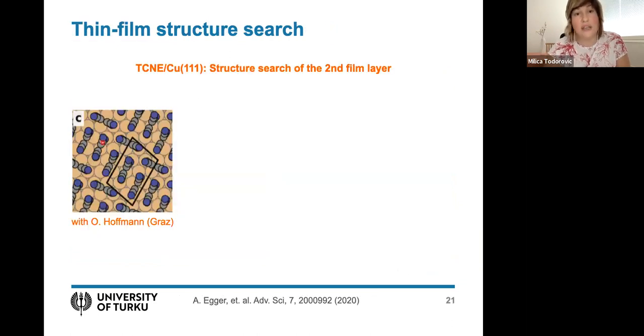Okay, so now let's look at a different example. Let's say that you have studied already your molecules adsorbing to the surface. This is what we did in collaboration with Oliver Hofmann. We were looking at TCNE adsorbing to copper 111 again. And Oliver's code SAMPLE analyzes the potential adsorption sites on the surface, and he used it to build this monolayer structure, which is the most favorable monolayer. But now after the monolayer forms, the question is, how does the second layer form on top of this? And now all the adsorption sites have been saturated on the surface. So where are now the adsorption sites on top of the first monolayer?